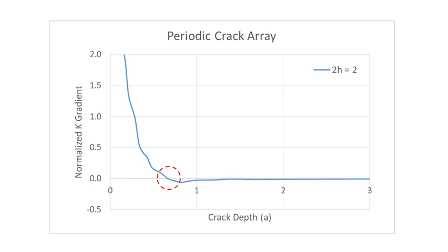Now, this implies that a crack is going to go dormant once it reaches 2/3 depth. I think anybody that's familiar with stress corrosion cracking and is up on the industry literature will know that it's quite common for cracks to go dormant. There are various explanations for this. I'm going to be looking at it entirely from the perspective of the fracture mechanics and the K considerations. There are some people that will argue that cracks will go dormant, but then ultimately come back to life and continue to propagate. And that's something that has been addressed by Parker, the author of the paper that I mentioned before.